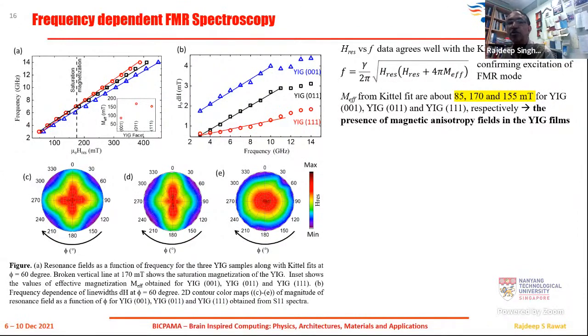And in order to explore the effect of the crystal anisotropy, the crystal symmetry, we did the phi scan. That means your applied external magnetic field was rotated in plane through 360 degrees. The corresponding results are shown here. But before I go to the angular dependence measurements, first of all, the frequency was changed, and at all these different frequencies we got these spectra, and from there you get these plots shown in results A and B.